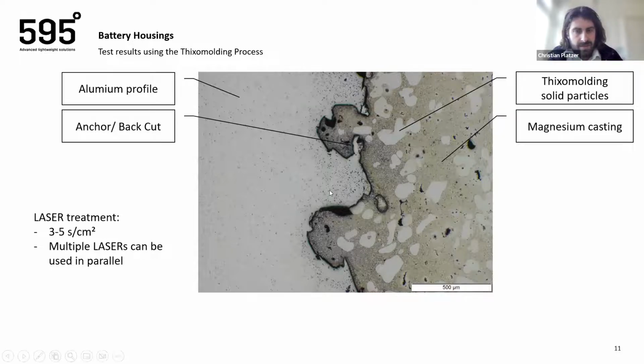The laser treatment that was so far most successful had a speed of 3 to 5 seconds per square centimeter. This is quite slow if you want to make big battery housings, but technically it's possible to also use multiple lasers to increase the cycle time. The lasers that are being used to do this are conventional lasers that can be bought on the market. Usually the IPR for the laser structures is the parameters that you use to create the grooves and then the microscopic structures of this interface.